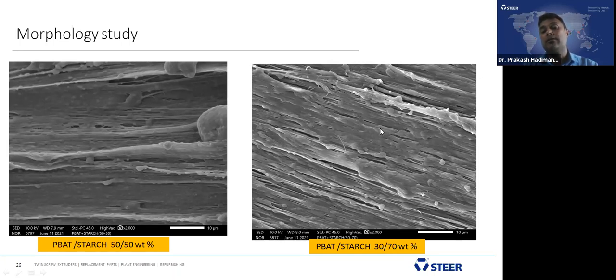surface, because the polymer content is less, the viscosity increases, but the dispersion was very good. You see the starch particles here, these are the starch particles distributed and dispersed completely. Even though we get a reduction in the elongational strength, we are getting better other properties like tensile and other properties, so that can be utilized for injection molding applications.